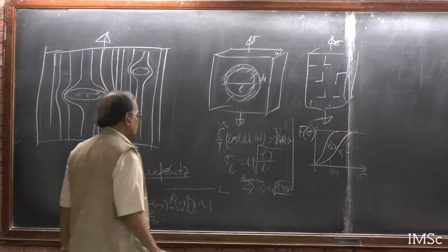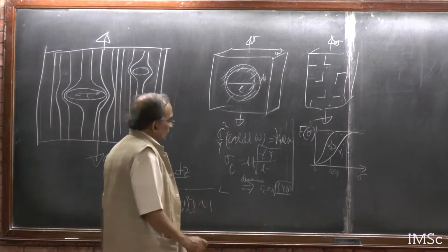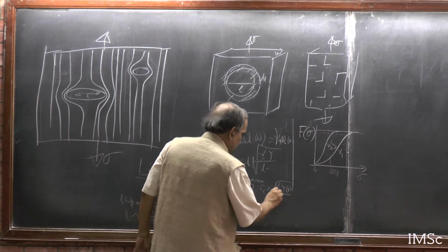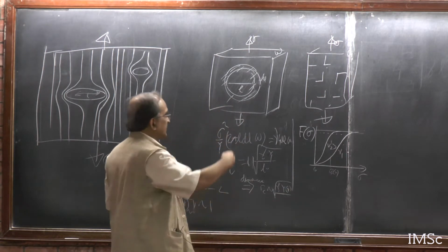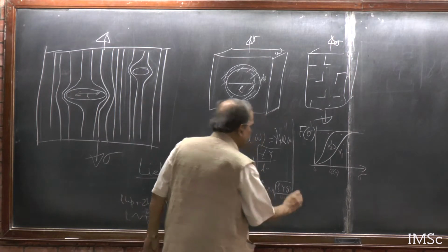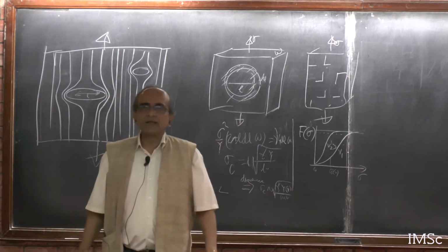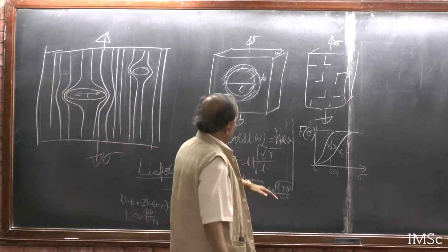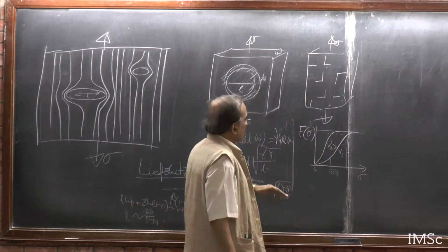It's a thermodynamically defined quantity. Even in the volume going to infinity limit, it is a defined quantity. It is dependent on P minus Pc, the percolation threshold, but it's a defined quantity. But here you will get log V. And that means you do not have in the V going to infinity limit anything.